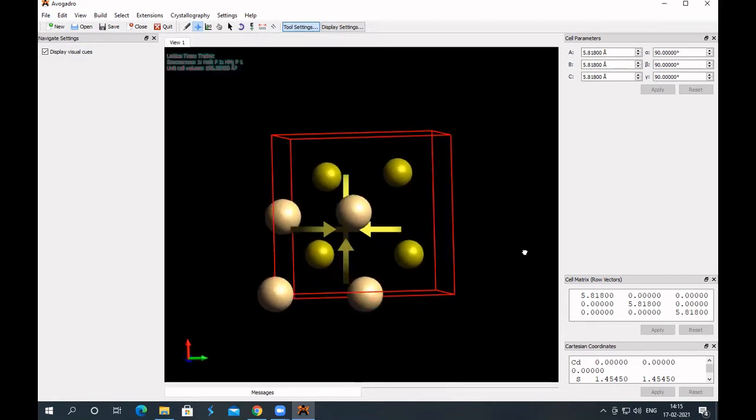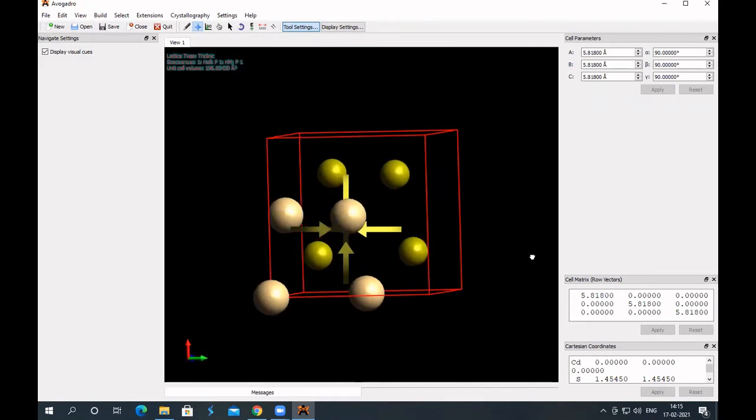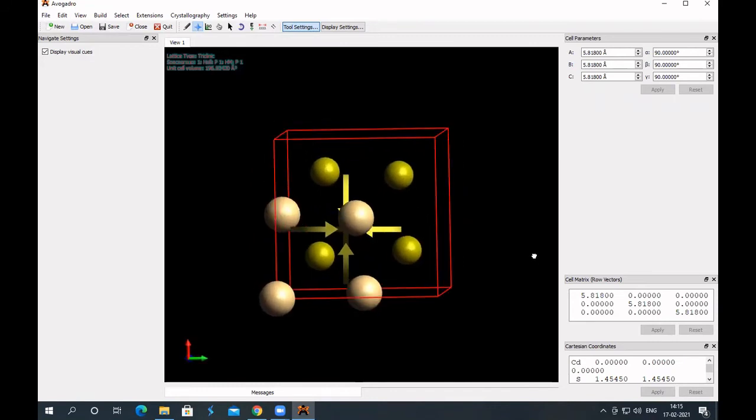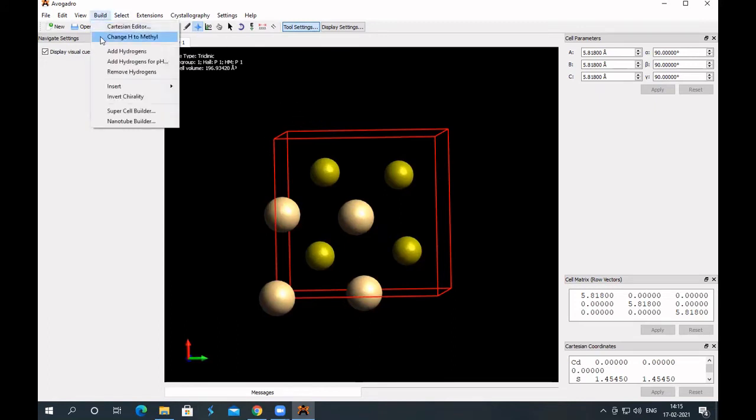So clearly this is corner and face centered, so each sulfide ion is surrounded by four cadmium ions in the tetrahedral fashion and similarly each cadmium ion will be surrounded by four sulfide ions in the tetrahedral fashion. Now let's try to build supercell. Go to build menu. The supercell builder. And then increase the number along the three directions. Click on generate cell. Close. You got a supercell. And now to obtain cluster, remove this unit cell because you are not going to do the periodic calculation. So there's option in crystallography menu. Remove unit cell. Click on this. Now you have cluster of atoms.